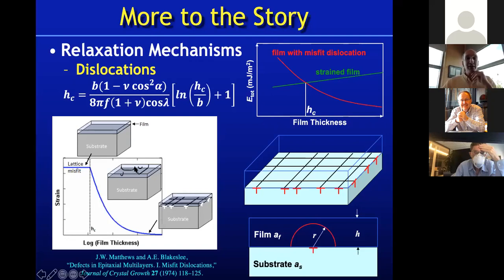One low energy nucleation path is the introduction of half loops from the surface of the growing film. And then those half loops, if they can move down to the interface and become misfit segments, like I've shown here on the schematic on the right, that can proceed. That takes film growth. So you shouldn't be thinking about the strain going away suddenly, from fully strained to fully relaxed. What happens in real films is that when one goes beyond the critical thickness, and often substantially beyond it, just to give you a rule of thumb, for many of the perovskites that we make, we can go about a factor of 4 thicker than the equilibrium critical thickness that you calculate from this Matthews-Blakeslee formula before we start to see the onset, where we can just start to resolve, using a synchrotron because the films are thin, relaxation. Typically it's a factor of 4 thicker.